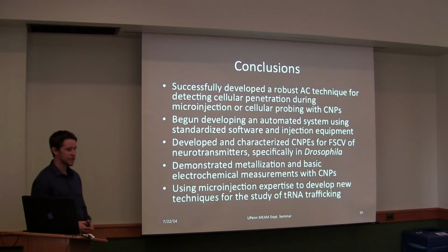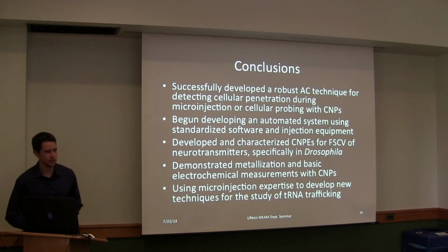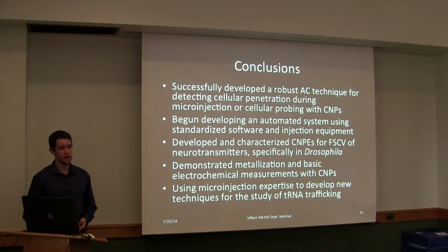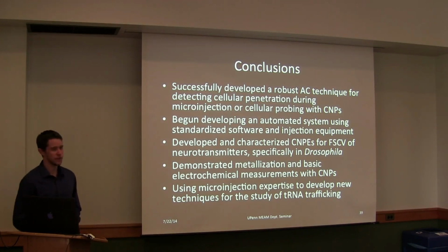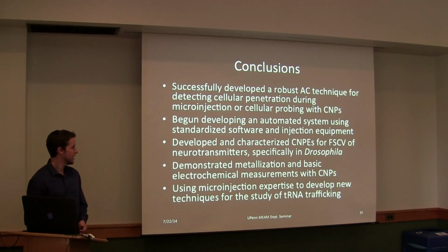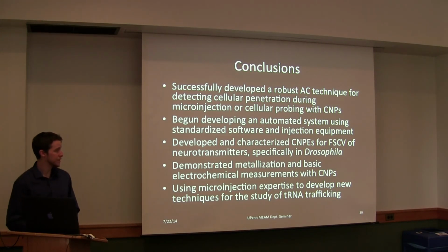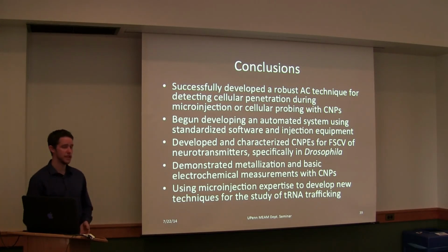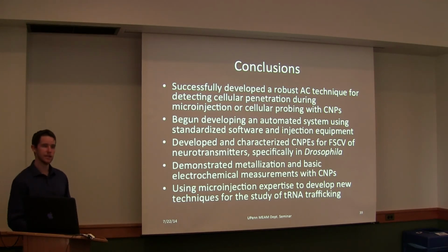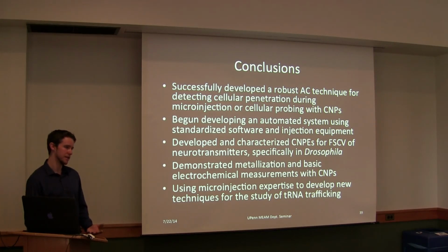So in conclusion, we successfully developed a robust AC technique for detecting cellular penetration both during microinjection and cellular probing, even when the CNP is at the nanoscale. We've begun developing an automated system using standard software and microinjection equipment. We developed and characterized CNPEs, or CNP electrodes, for fast scan cyclic voltammetry of neurotransmitters, specifically in Drosophila melanogaster. We demonstrated metallization and basic electrochemical measurements, showing the versatility of the carbon electrodes and how we can functionalize them for different purposes. And we used our microinjection expertise to develop new techniques to study tRNA trafficking across the cell membrane, or across the nuclear membrane.